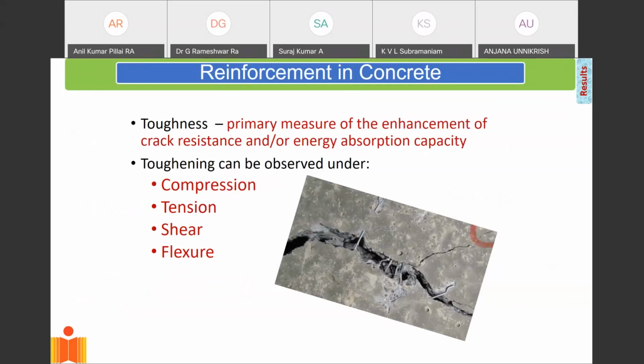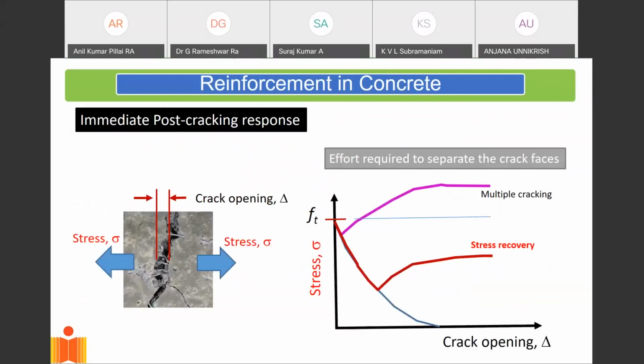They toughen the material, they increase the toughness of the material. Now the material is able to absorb a lot more energy, and basically I'm able to design using this material. And one of the ways we look at toughness is to see how much effort it takes for us to pull the piece of concrete apart. Because concrete is a very brittle material, once a crack forms, the crack quickly grows and we're able to separate the material. So if you look at the stress that it takes to separate a piece of concrete, that is shown by this light blue line here.